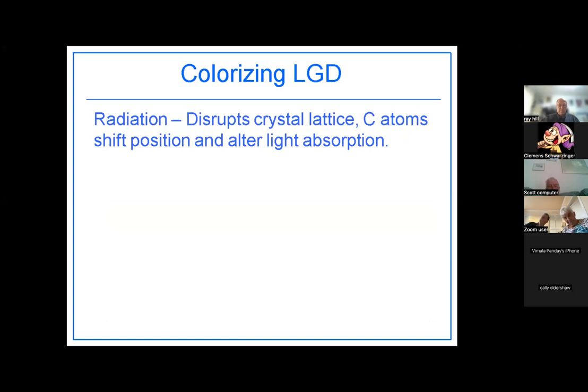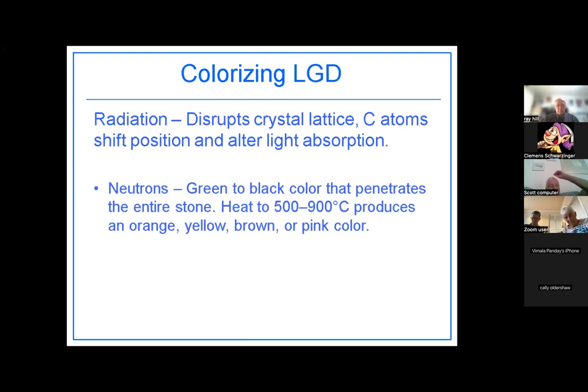Now, when it comes to colorizing your lab-grown diamond, you can use radiation. This actually disrupts the crystal lattice, just like it would, say, in the Dresden green diamond for natural diamonds. And what happens is that your carbon atoms shift their position in the crystal a little bit, and it changes their light absorption properties. And in the case of the Dresden green, the resultant color is obviously green.